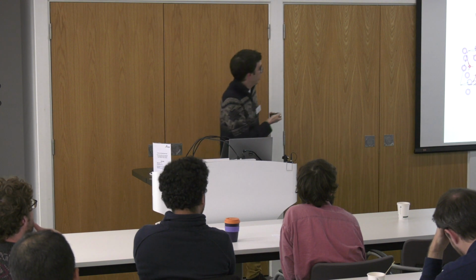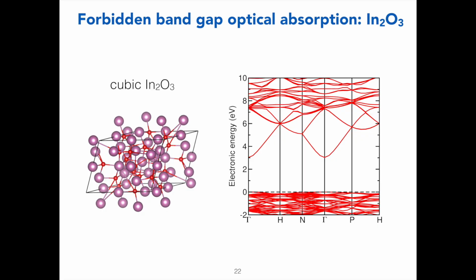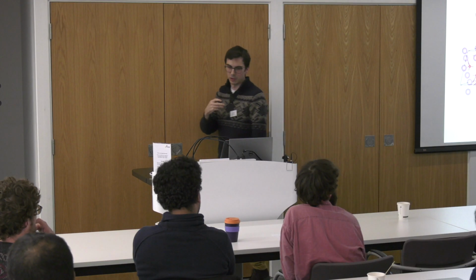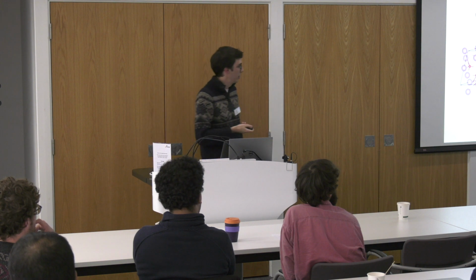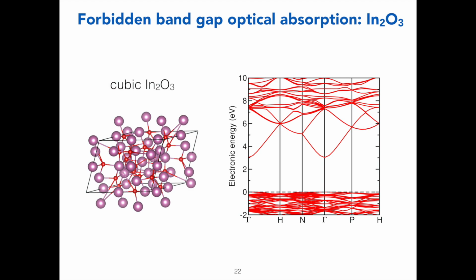So the example I have here is for cubic indium oxide. Again, this is actually the most widely used material as a transparent conductor. And again, you can look at the band structure and see clearly why that is. You have a big band gap from the valence to the conduction band, and then if you dope it here, you again have a big band gap to the next conduction band. So the material stays transparent while it's conductive. And this material, like the one I showed earlier, is actually direct band gap. So the top of the valence band is indeed at the gamma point, and the bottom of the conduction band is also at the gamma point.